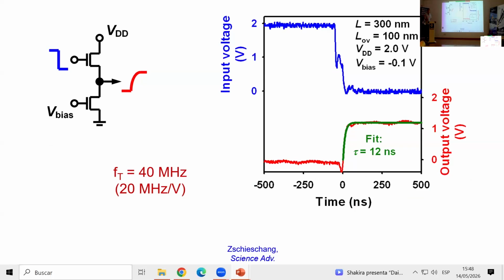Okay. But now, most importantly, to the dynamic performance of these transistors. Remember, most of what we've done here was done with the intention of maximizing the transit frequency, of being able to operate these transistors with as high a transit frequency as possible, ideally a transit frequency greater than about 10 megahertz. And so here, to measure the transit frequency of a field effect transistor, what we do is we actually make two transistors and we connect them in series so that we can use one of the two transistors as the one that switches, and the other one basically as a resistive load, so that we can get the voltage response here at this output node.